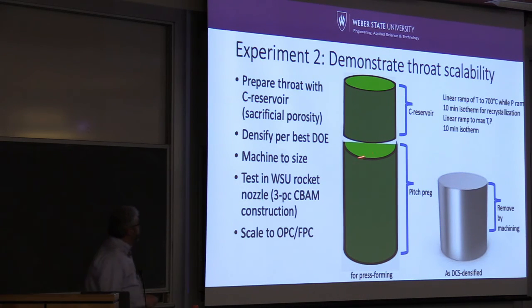So what I wanted to do was to make, instead of that thin little puck, I wanted to make it much thicker and then put a whole bunch of pitch on top of that as a carbon reservoir, run it through the DCS tool, densify it. So most of the porosity would have occurred up here. The compression would have resulted in something where, okay, I've got porosity up here and I've got a gradient down to the dense material here. And then remove what you don't want with machining, drill a hole in it, and you've got yourself a nozzle throat, which can be built into a nozzle. And then we can go and test it and have some real fun.